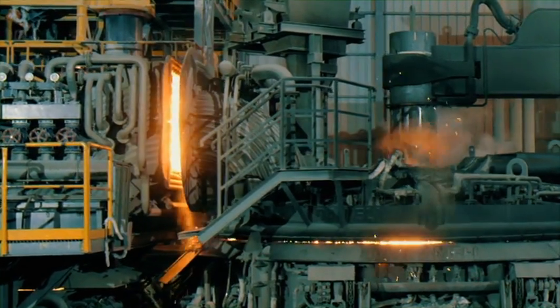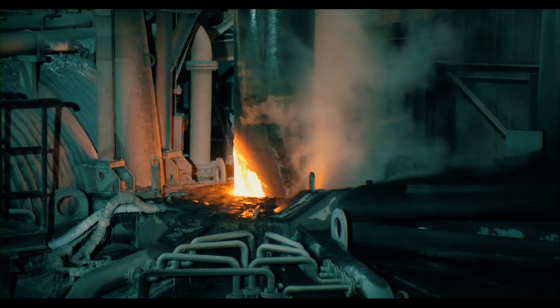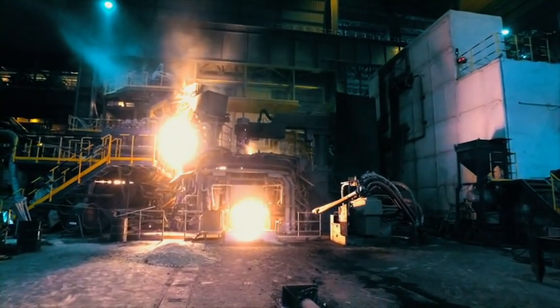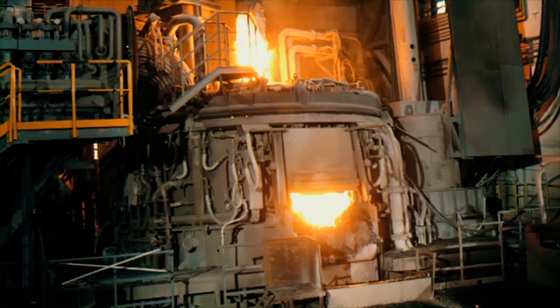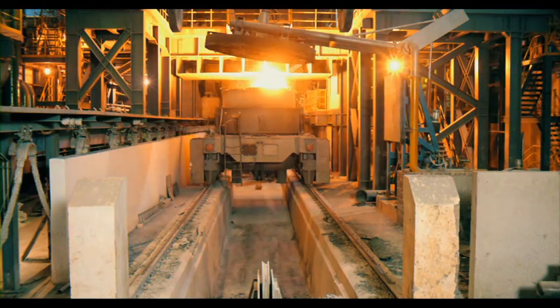Oxygen and carbon are then introduced into the melted steel with the help of an injector. Oxygen reacts with different components in the steel bath, and carbon, phosphorus, manganese, silicon, and aluminum oxides are formed. These oxides are lighter than molten steel and therefore float above as slag. This slag primarily contains impurities that are poured off by tilting the furnace at a 15-degree angle. At the end of this process, molten steel is collected in a ladle by bottom tapping.